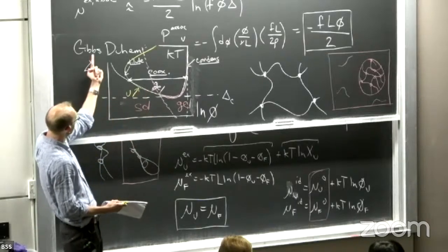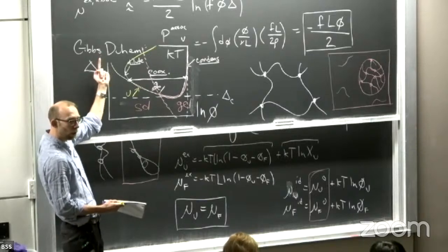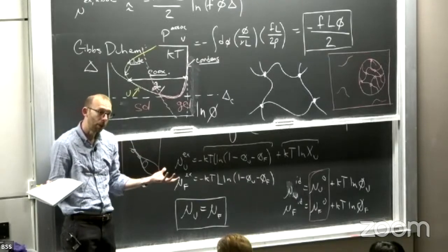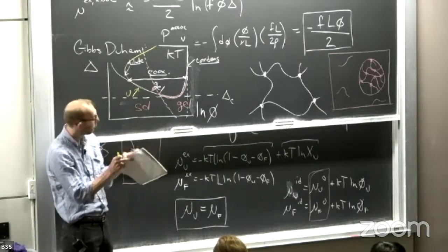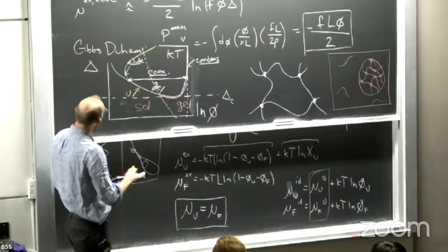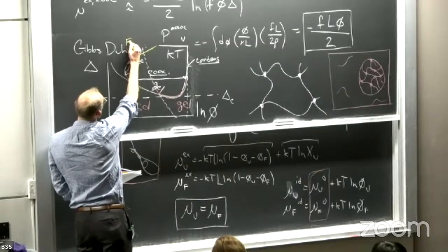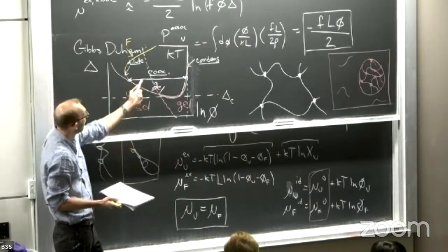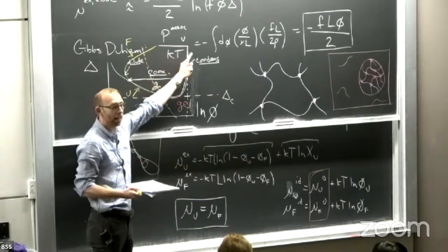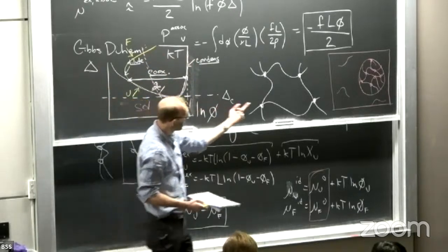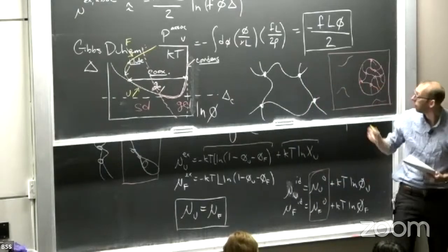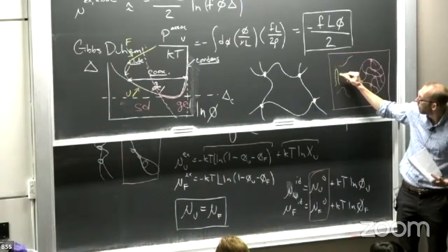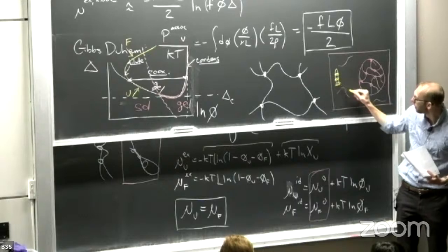But as I make this association parameter stronger and stronger, I should expect that in the dilute phase, I'm going to overcome this conformational entropic cost to fold, to be able to form all these intramolecular bonds. And so I should get this F state. And ultimately, as I go in this direction, I'll have approximately the same number of bonds in both the dilute phase and the condensed phase. In the condensed phase, I have this system spanning network here. But in the dilute phase, I have an equal number of bonds because I can do this.